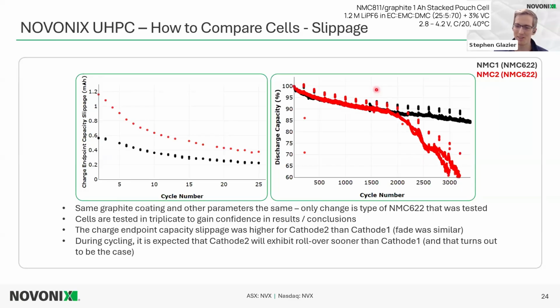Another shameless plug for our last webinar that we did with UHPC, which was called Ultra High Precision Coulometry. And really, this comes down to the accuracy of a system. The accuracy is the ability to measure how close you can measure to the exact current that's going through your cell. Every charge-discharge cycler has an inherent bias, channel to channel, it varies, and within charge and discharge. So if your charge is always slightly overcounting and your discharge is slightly undercounting, then you're always going to have a bias towards a much higher slippage. And if the opposite's true, you may even be counting a negative slippage.